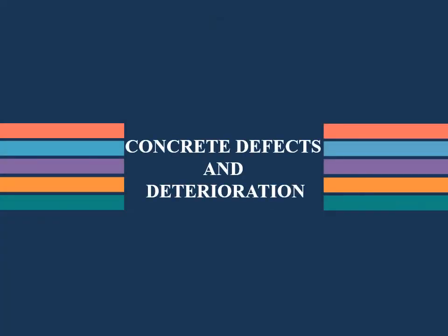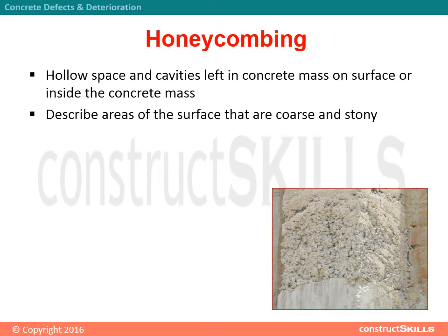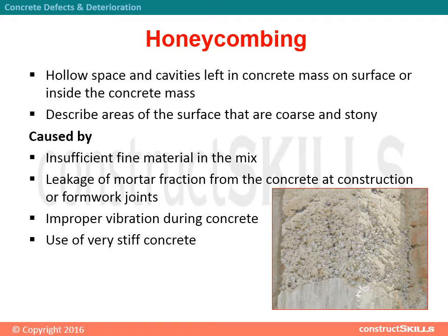Concrete Defects and Deterioration: Honeycombing. Honeycombing refers to hollow spaces and cavities left in the concrete mass, either on the surface or inside. It describes areas of the surface that are coarse and stony. It is caused by insufficient fine material in the mix, leakage of mortar fraction from the concrete at construction or formwork joints, improper vibration during concreting, and use of very stiff concrete.